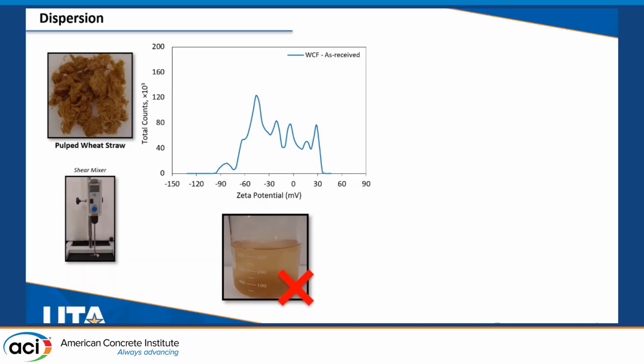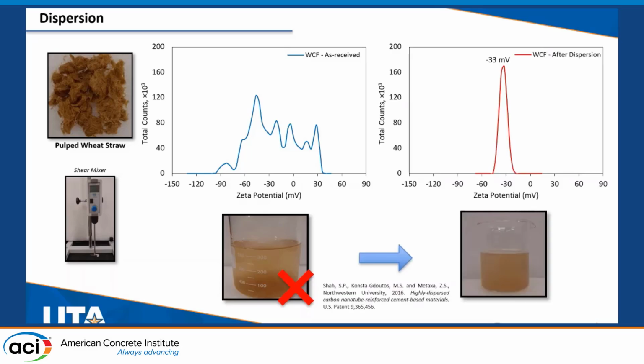unstable suspension. To overcome this issue, I followed the dispersion technique patented by Professor Shah and Professor Konsta-Gdoutos using surfactants that resulted in a monomodal distribution of zeta potential values that led us to a suspension with improved stability that is suitable to be used in construction materials.